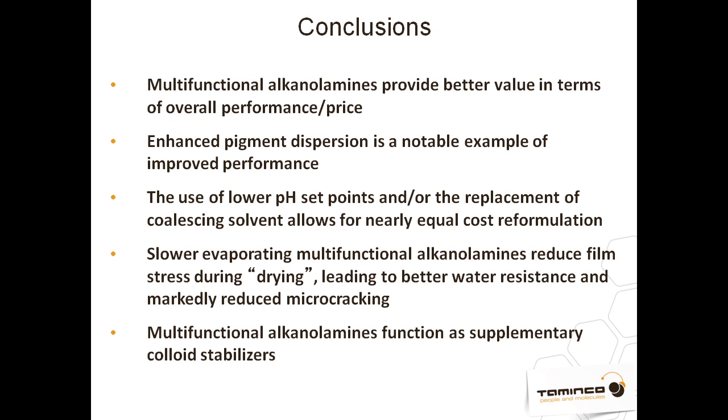Slower evaporating multifunctional alkanolamines not only result in lower odor, lower VOC formulas, but they can also lead to better drying, less stress in the coating during the drying process, which can result in film improvement benefits. And finally, just in general, multifunctional alkanolamines, multifunctional additives in general can function as supplementary colloid stabilizers across the gamut of colloid systems that exist in paint.